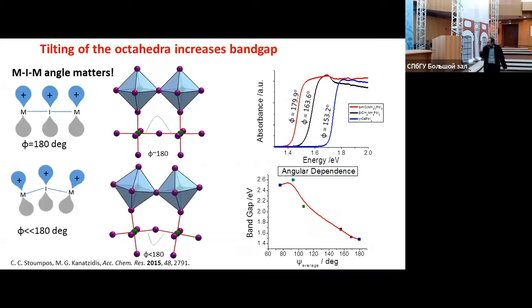And why do we care? Because the tilting angle that connects the metal and the halogen, especially the metal-halogen-metal bond, determines the orbital overlap, and effectively decides what the band structure should look like. For a nearly linear angle, that's the maximum orbital overlap you can have, and you turn out to have the smallest bandgap. This is the case for the alpha formamidinium lead iodide. When you start tilting, the orbital overlap reduces, and as a result you have an increase in the bandgap. And if you tilt too much, that's the beta methylammonium lead iodide.